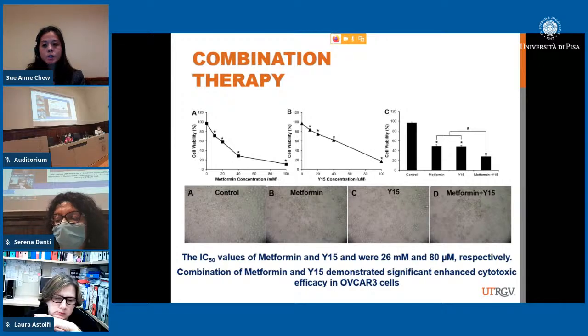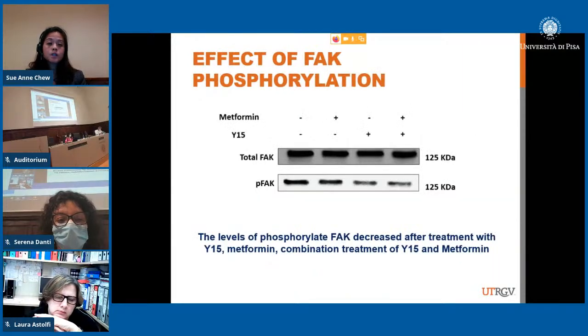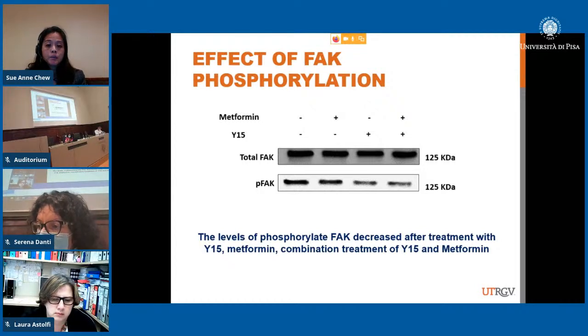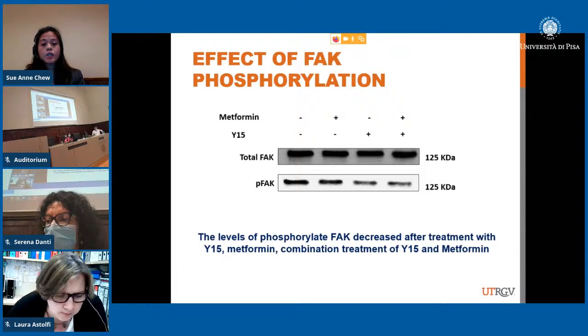So over here, in a 2D model, we saw that combining the metformin and Y15, we can get a synergistic effect compared to the solo drugs when they're delivered individually. So how it works is, the FAK inhibitor Y15, you would expect it to decrease FAK phosphorylation. FAK is a kinase, so the way it works is by phosphorylation. But metformin hadn't been explored as much before. We saw that it's also able to decrease the phosphorylation of FAK. So, with these two combined, we hope they can combine and be synergistic and decrease it further.